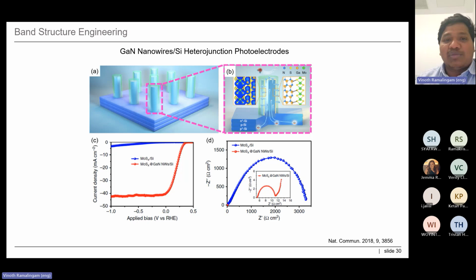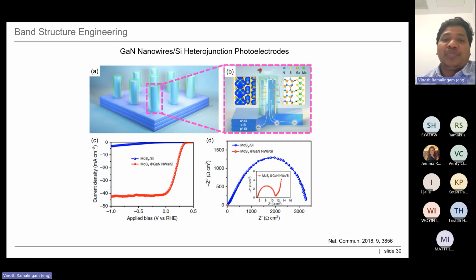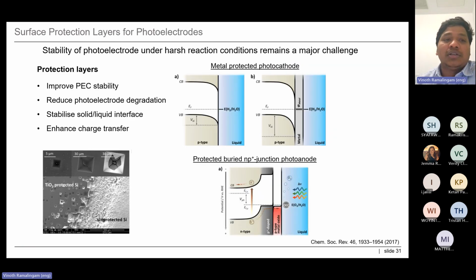There is another example of gallium nitride nanowires with silicon heterojunction photoelectrodes, where you see that when they form the heterojunction with the silicon, the performance is really improved a lot. For example, without gallium nitride nanowires, they reach only close to 5 milliamps of current, and after it forms a junction, the current density is really improved and the onset potential is reduced a lot. That means when you form a junction of two different materials that absorb different regions of light, it also improves the charge carrier separation to facilitate better PEC performance.